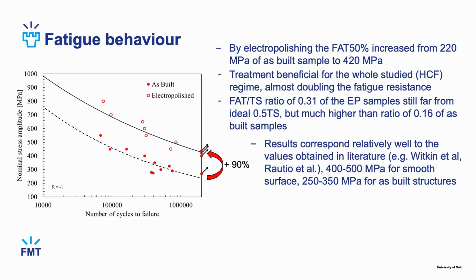So the fatigue itself. By just electropolishing the samples, we can immediately see that we increase the fatigue behavior, and the FAT, the fatigue limit, 50% probability limit, increased over 90%, from 220 megapascals to 420. And the treatment seems to be beneficial for the whole high cycle fatigue regime.